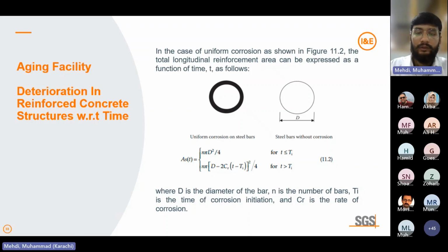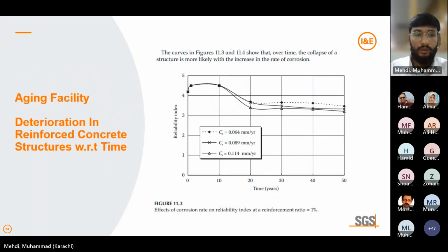In the case of uniform corrosion, as you can see in these figures, the total longitudinal reinforcement area can be expressed as a function of time, where t is the time, D is the diameter of the bar, N is the number of bars, Ti is the time of corrosion initiation, and Cr is the rate of corrosion. So equation 11.2, as mentioned here, takes into account the uniform corrosion propagation process from all sides, and overall over time the collapse of the structure is more likely with an increase in the rate of corrosion. In these curves, you can see that we highlighted the pattern of deterioration of the steel reinforcement.